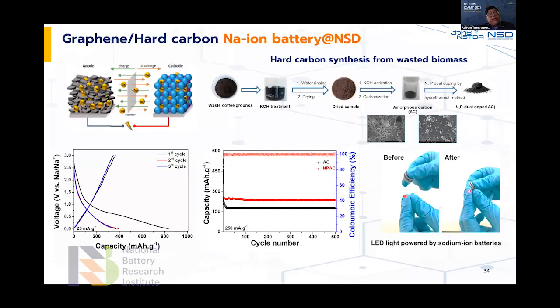So in our center, we put graphene into the sodium-ion battery in various forms, such as mixing it into the anode system. Also, we use our wasted agricultural material to make hard carbon, which is one of the important materials for the sodium-ion battery, because in the anode we can have hard carbon as an anode. And this shows the performance: our capacity is up to about 400 milliamp hour per gram, which is quite impressive. And also the number of cycles has now been proven at more than 500 cycles.